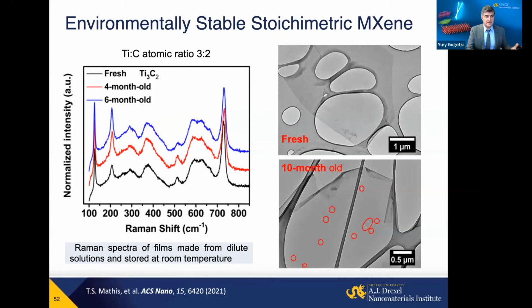Now, if you take titanium carbide Ti3C2, as long as you have a proper atomic ratio, so few vacancies in the initial structure, and make quality flakes of MXene with a minimal number of defects, then as you can see, stored for 6 months in dilute solution in a closed vial in water, there's no change in Raman spectra. After 10 months, just a couple of pinholes appear in the layers. So if you put it in low temperature storage in highly concentrated solution, you can store it basically for months.